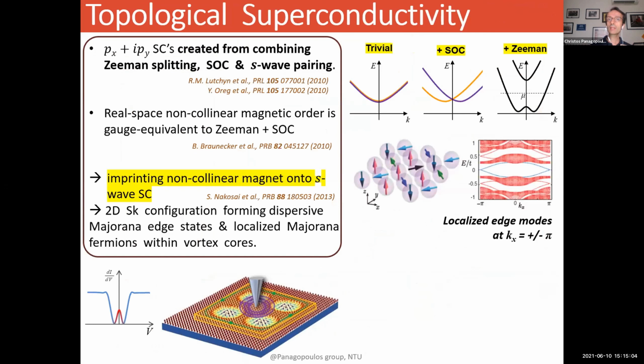Now, and this is important because it can lead to topological superconductivity in a platform that you can actually manipulate, that is, engineer. And that means you can create topological superconductivity from combining Zeeman splitting, spin-orbit coupling, and S-wave pairing. So in real space, what you will have is non-collinear magnetic order, which is gauge equivalent to having Zeeman plus spin-orbit coupling. And therefore, imprinting a non-collinear magnet onto an S-wave superconductor would give you a two-dimensional skyrmion configuration forming dispersive Majorana edge states and localized Majorana fermions within the vortex cores.